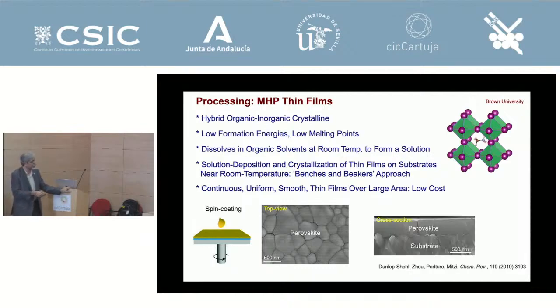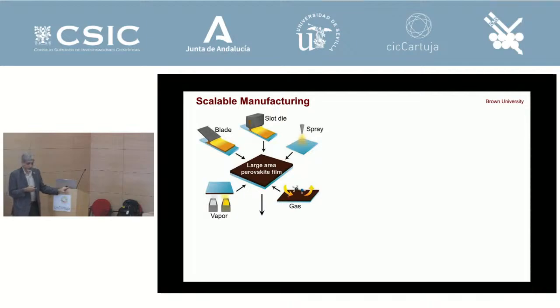So you typically need about a 500 nanometer film. More than that, it becomes parasitic. So 500 nanometers absorbs all the light that you'll need because it's such a good light absorber, right? And so the whole solar cell active region is 1 micron. That's really amazing. There's hardly any material needed, and it still gives you efficiency the same as silicon, right?